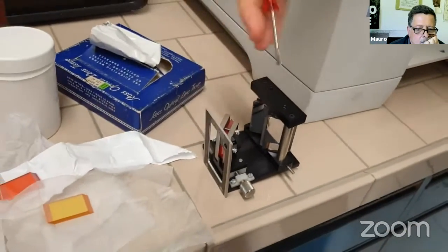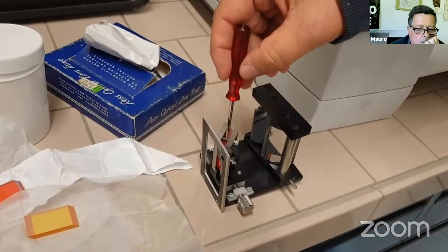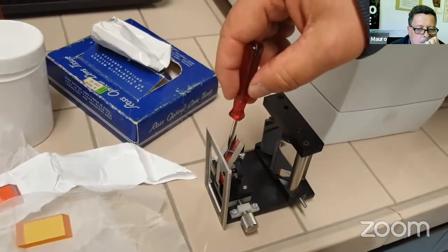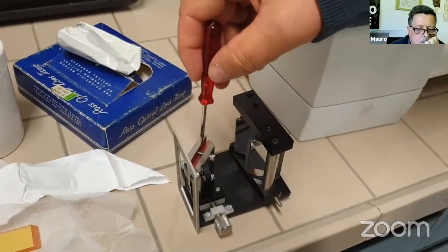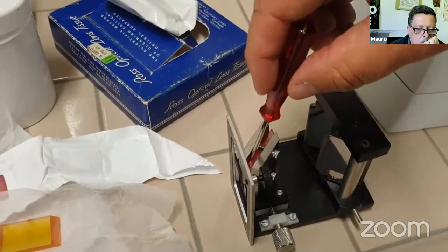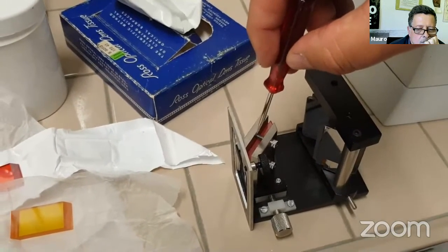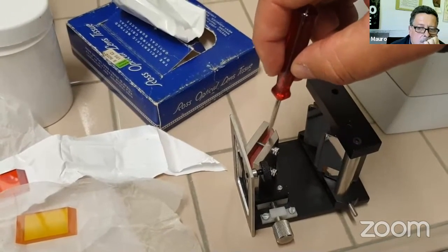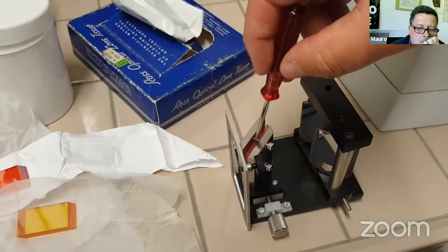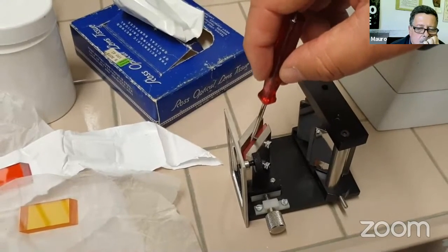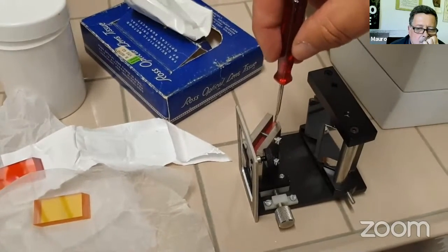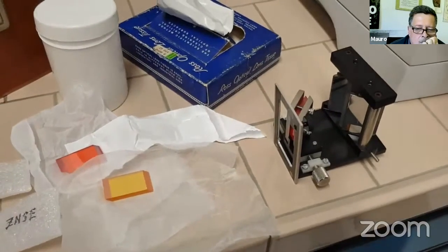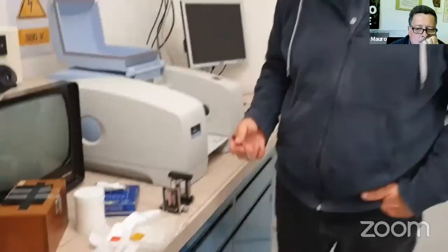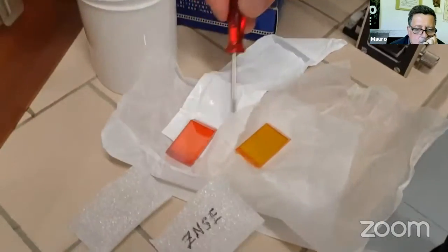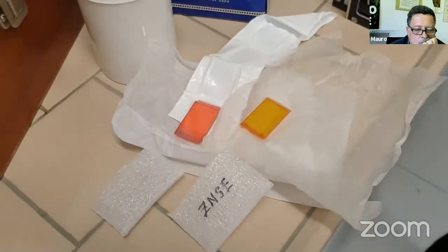Instead of transmission, here we have a different sample holder which has a prism, and the infrared light bounces on the prism surface, and the sample is kept between one of the prism surfaces and the plate. And each time the infrared light bounces on the prism surface, it samples the material at the surface boundary. And then after some reflections, the light comes out. So this is actually a means to increase the sensitivity of the measurement and also to measure very small amounts of samples. You can change the prism using different infrared materials to optimize the spectral interval of interest.